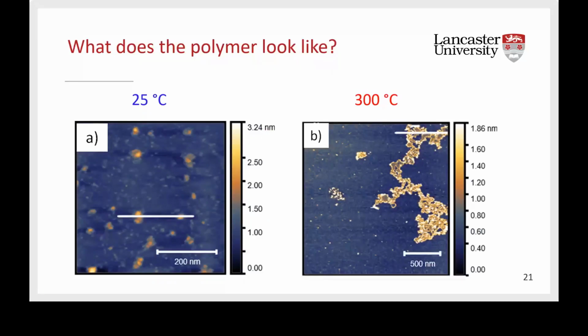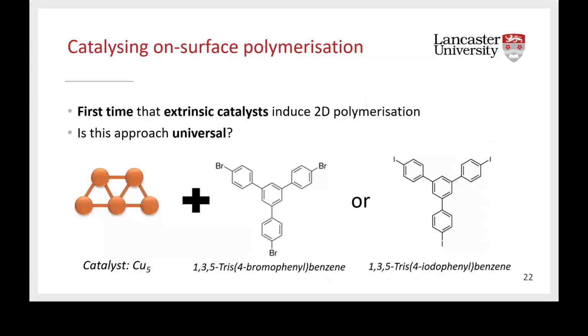So in figure A, you can see an AFM scan of the Cu5 plus the bromophenyl benzene on a mica surface. And in figure B, you can see what happened after this has been annealed at 300 degrees Celsius. We can see the formation of this orange island, which is the polymer. The same results were replicated on HOPG and even gold 111. So this is the first time that an extrinsic catalyst has been used to induce two-dimensional polymerization on inert surfaces.